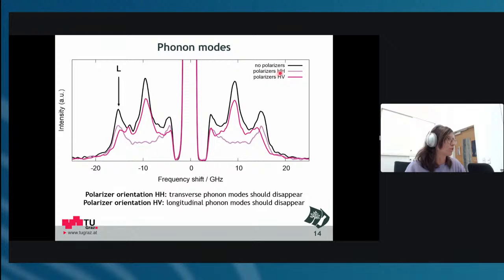And then when you use the polarizers crossed, so you have the polarizer before the sample in horizontal orientation, and when it goes through the sample before it goes to the spectrometer, it's in vertical direction. So here you should now just see your transverse phonon mode, and the longitudinal phonon mode should disappear. That's, as you can see, not as clear as in the other case, but that one is still very nice. This is clearly a transverse mode, and here you have what I was mentioning. It's a quasi mode, like a mixed thing.